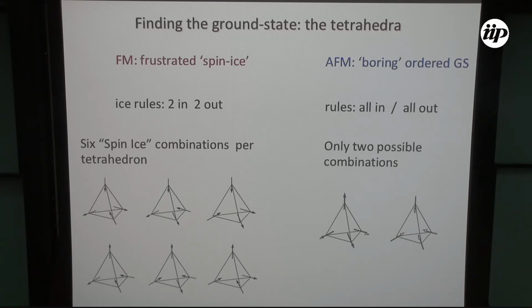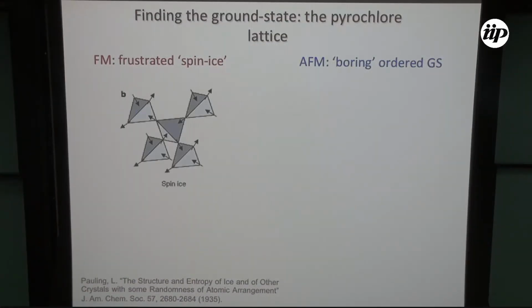So what happens when you put many of these together and you build a lattice? What sort of ground states do you get? In the case of the frustrated ferromagnet, this is what has been called the spin ice. The reason for the name ice is because essentially what you get is the same entropy of the ground state as what you get in water ice. When you put all these together, now you have a further constraint, which is, of course, when you put 2 tetrahedra together, the spin has to be the same at that vertex.